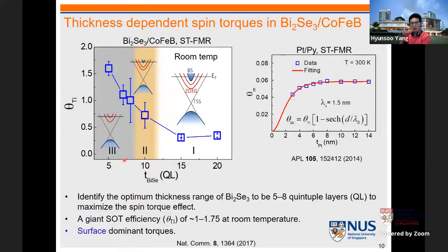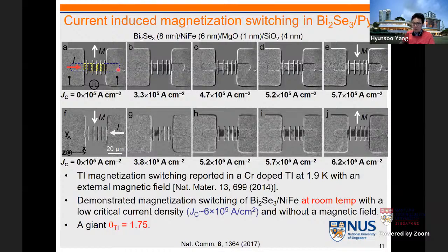So we just chose a quintuple layer thickness because we need to think about the effective spin Hall angle, but at the same time, junction resistivity. If we use too thin films, basically the effective spin Hall angle is very large, but the junction resistivity will be huge. So the power consumption will also be very high. So by choosing 8 nanometers, we deposit nickel iron on top, then we can chop down this nickel iron into a few or several pieces, with different anisotropy and coercivity.